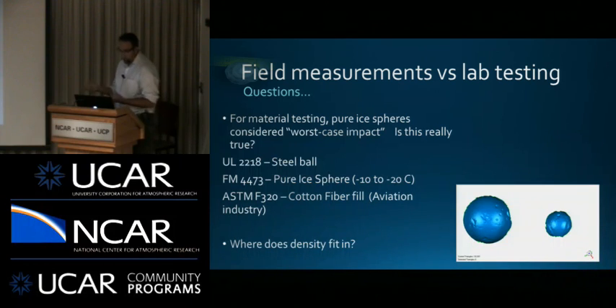So for material testing, pure ice spheres, is it the worst case impact? Is that really true? I don't know, but is it reasonable to consider just kind of a mean state? Probably so. So that's probably a better way beyond the steel ball test to test a shingle material or something like that. The standard test from FM Global, which is a risk insurer, is an ice sphere, but it is not the product accepted. The one that everyone uses is this UL 2218, which is the steel. It's simply a steel ball drop. So it's simply kinetic energy onto a building material.